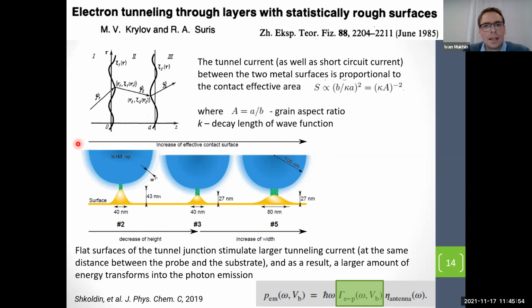It can be shown by this simple image. We consider surfaces with different grain sizes, and it's clearly seen that if you decrease the height of your grain, you increase the effective area through which the electron can tunnel. In the same way, if you increase the diameter of your grain, you have the same situation. So this simple experiment shows that in order to increase the efficiency of light emission, you need to make your substrate as flat as possible. It's quite contradictory to the first experiments with flat crossed stripes. Do you remember? In that case, the SPP wave was excited, was launched, and you need some roughness to convert it into far-field photons.